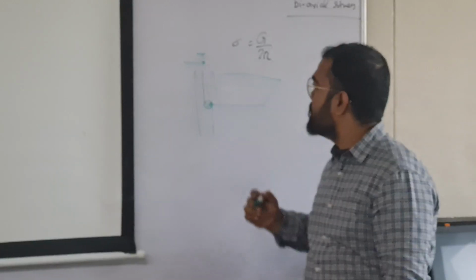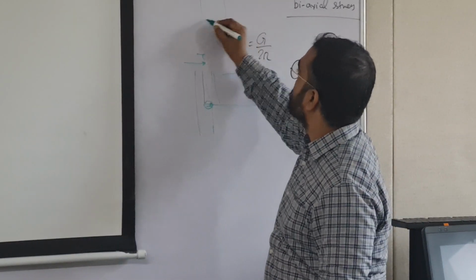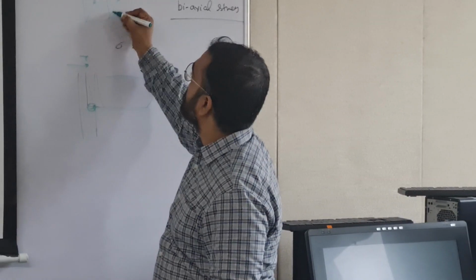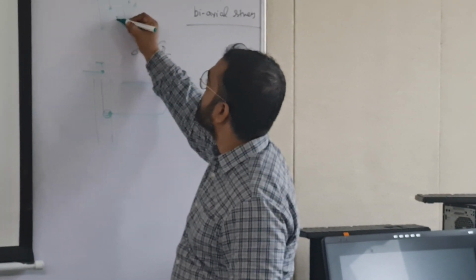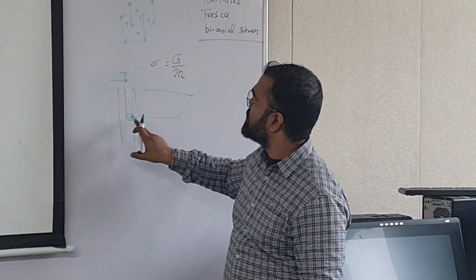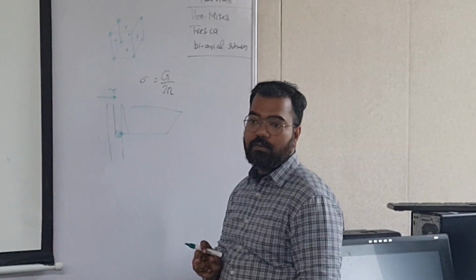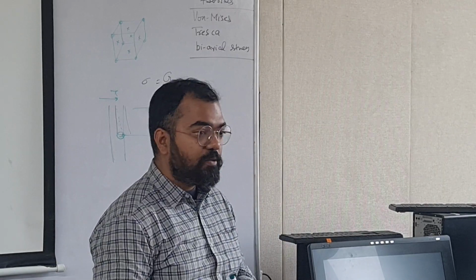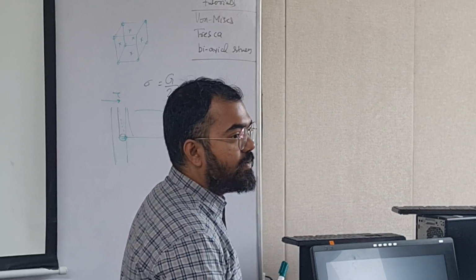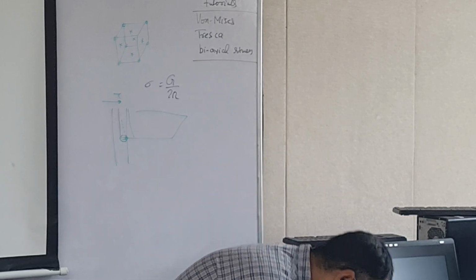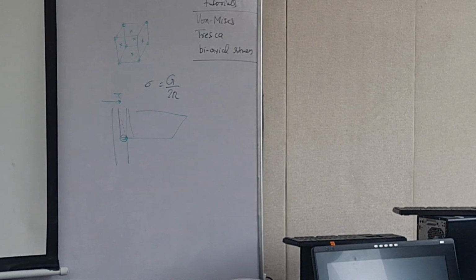A is the lattice parameter, so you can try making an FCC, okay? You just have to make a cube and then you have atoms on the corners and you have atoms on the faces, okay? So what do you think will be this value? One step of dislocation movement. A by 2? Root 2. A by root 2. Why are you saying that? Because of the plane in which it is moving. And what is that plane? 111. Good.